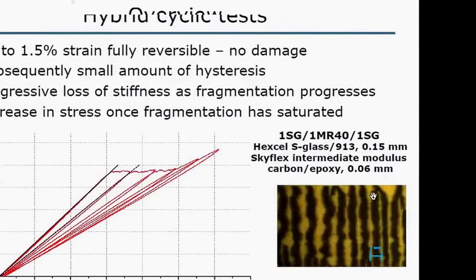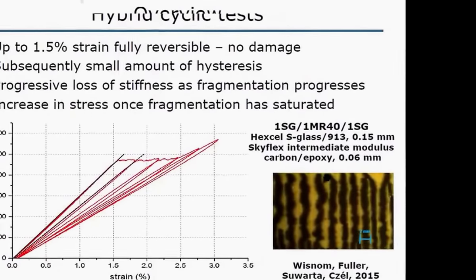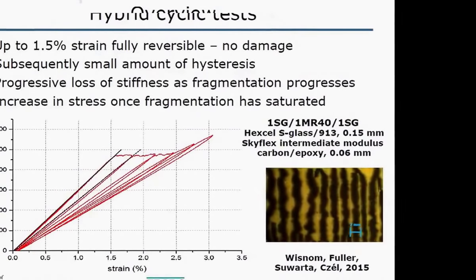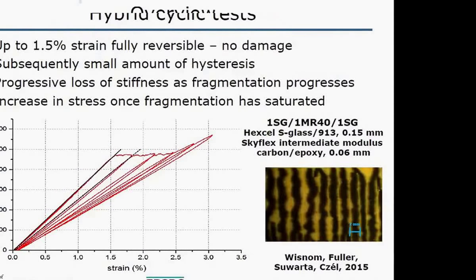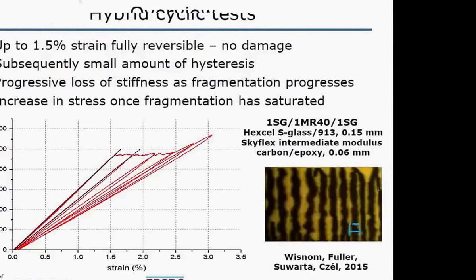You can do the same thing with, okay, this just shows what happens when you unload it. It's actually a different combination of materials, but when you load it and then you unload it, then initially, up to about 1.5% strain, it's just elastic, there's no damage, it just goes back down the same line. When you exceed the fragmentation strain, the strain of the carbon rate, then you've got a reduced stiffness because you've got damage.